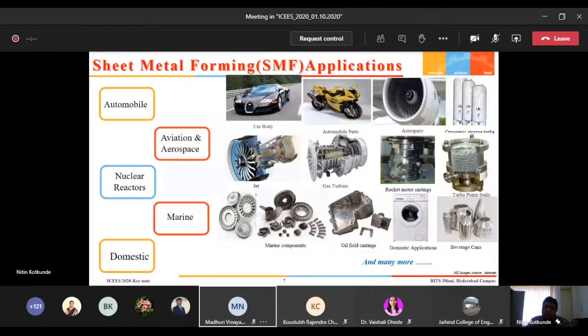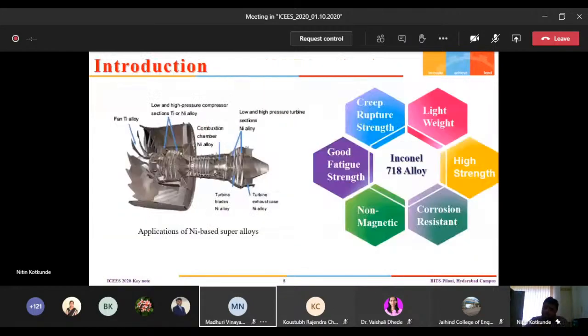The major challenge of these high strength alloys is that they have very limited ductility. Usually one of the basic requirements for any metal forming process is high ductility, so that the material can flow very easily and the desired shape can be formed. But the major challenge comes when you have limited ductility. Let us say titanium alloys have very limited ductility, less than 10% at room temperature. So you will see sudden fracture if you start forming the component at room temperature.